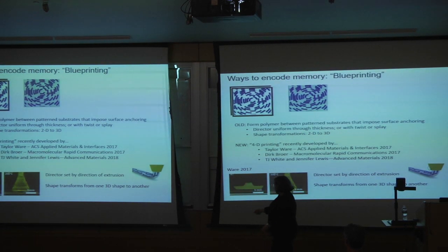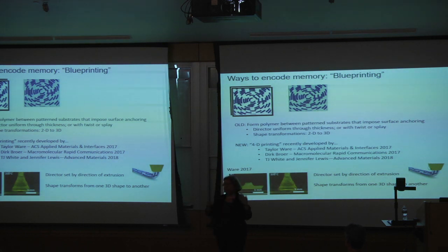And I tried to make a picture of that here. I think that's her picture. And then when that material was cross-linked and solidified, they would put it in water and it would swell, but it swelled less in the direction where the fibers were. That kind of prevented swelling. And so something that was printed flat would fold up into a flower shape. Very impressive. Okay, so we can do the same thing with liquid crystal elastomers.